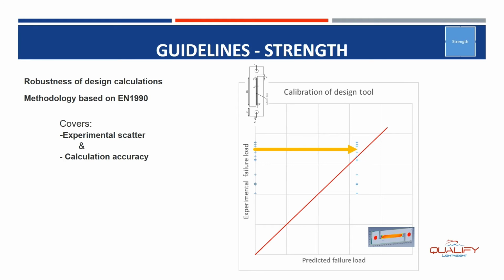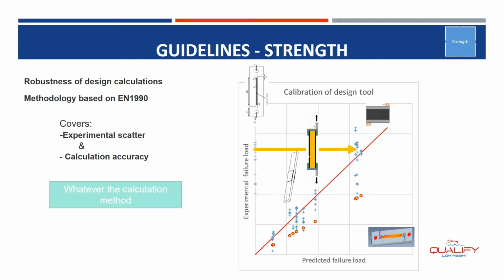In this diagram, we can plot the result. We have done that for one setup, and we can do it for different setups so as to assess the impact on the joint strengths of different loading, different configuration of design, etc. So we repeat the operation, experimental testing and calculation. We will get a cloud of points like this, which enables us to define, using this method, a factor to be applied on the predicted failure load so as to cover the experimental scattering, but also the calculation accuracy. This is true whatever the calculation method. It can be a very simple average stress method or a finite element cohesive element or something very complex. Then we have a large gain in confidence for the shipyard, for the owner, and for the class.